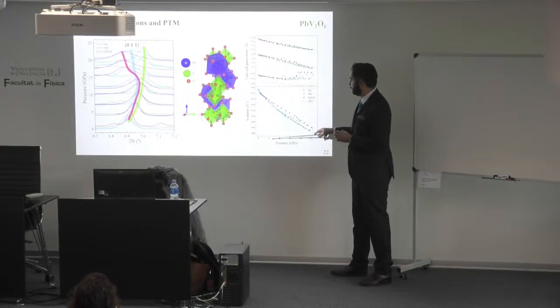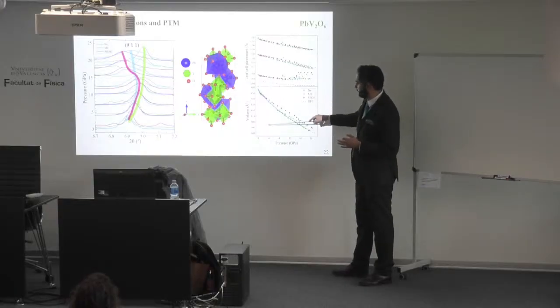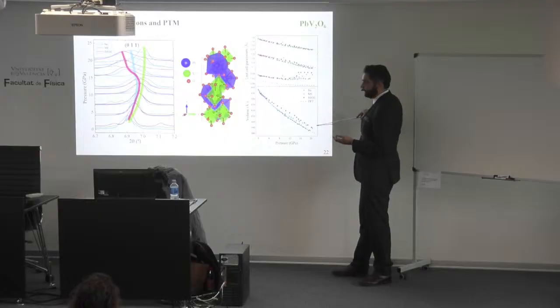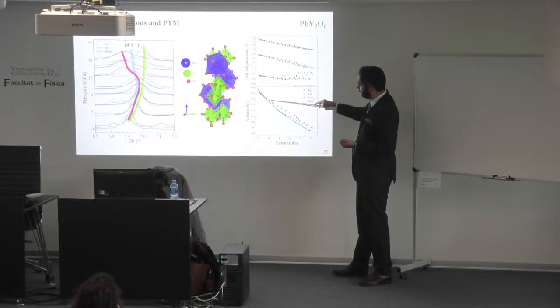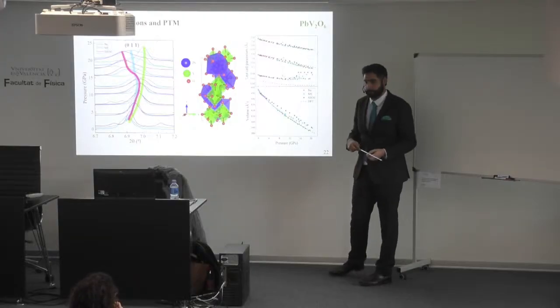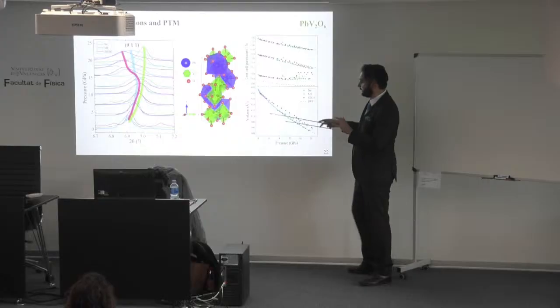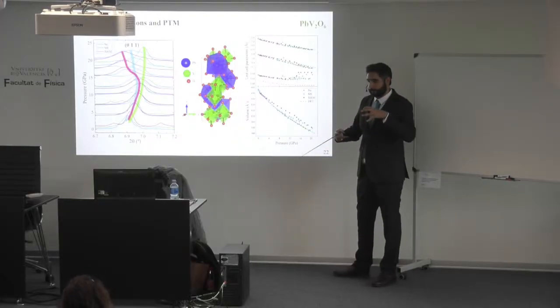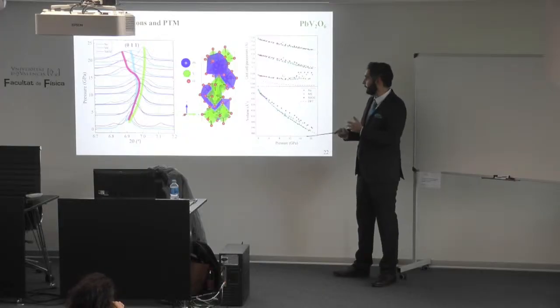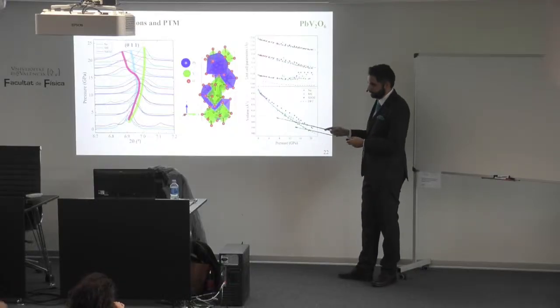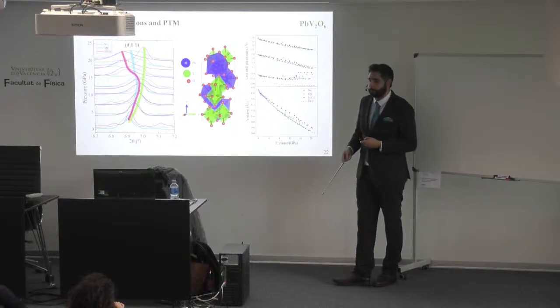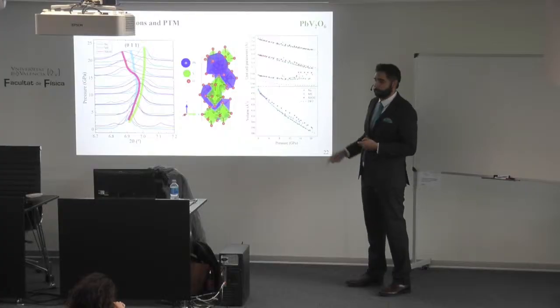So here with the volume, we see that perfectly with silicone oil, when it reaches the limit of around 3 gigapascals, it doesn't behave as expected. For the methanol-ethanol, at around 9 GPa, the same happens. And neon follows the line of the calculations. So in this case, the C and A axes are getting the most pressure, and as it is not hydrostatic, the B axis has to expand in order to conserve the equilibrium there. So this is not a phase transition, it's an effect of the pressure transmitting medium that we see because we had 3 different experiments.